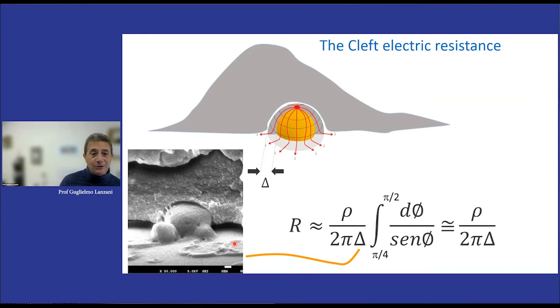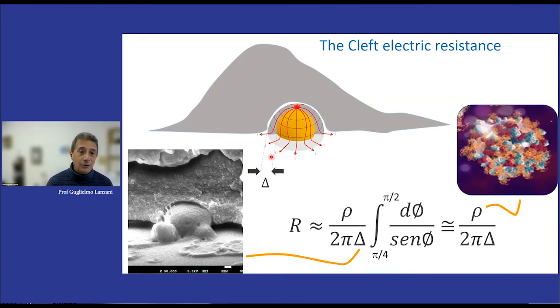And so the cleft is extremely small, and we are dealing with a sort of spherical shell of thickness delta, which is the current path that can bring the ions to the top of the particle, to the pole, in order to screen the charge. Now, how much is this delta? Well, that depends on estimation, but it's something below 30 nanometers. So it's extremely small. And what is the resistivity of the medium inside the cleft, in this spherical gap, this shell that is forming? Well, that is the resistivity of proteins, because a particle in a biological medium is going to be covered by a protein corona, which may establish islands of proteins that then establish a dielectric coupling.